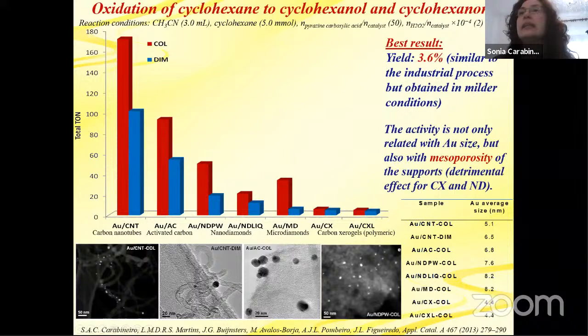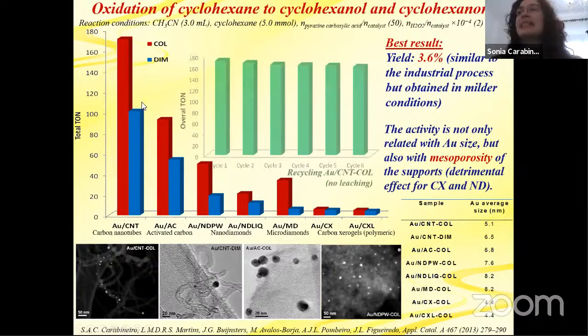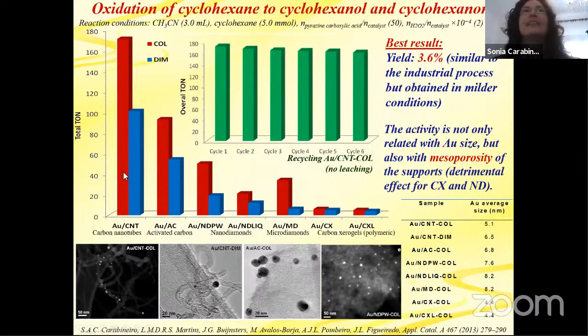So what we realized was that the activity was not only related with the gold size, but also with the mesoporosity of the supports, which seemed to have a detrimental effect, both for the aerogels and also for the nanodiamonds, which were also not so active. So we did a recycling test here of the best catalyst. And we see that up to 6 cycles, there is a very little decrease in the activity. There is no leaching of gold. So it was a quite good result.